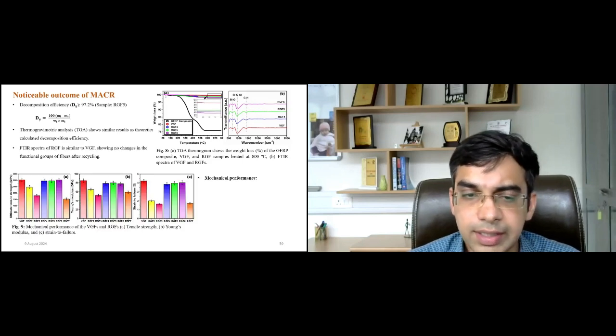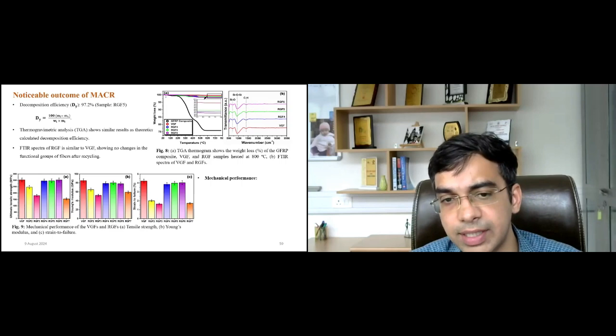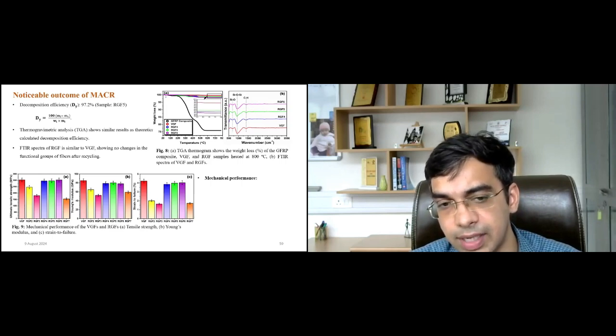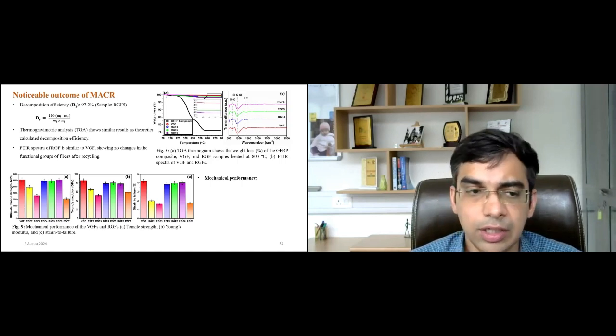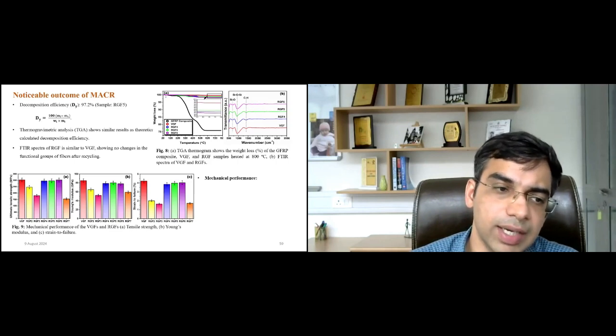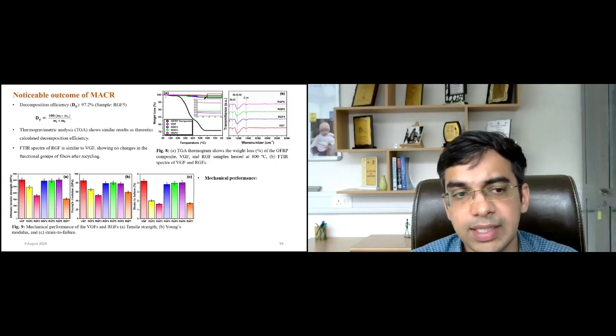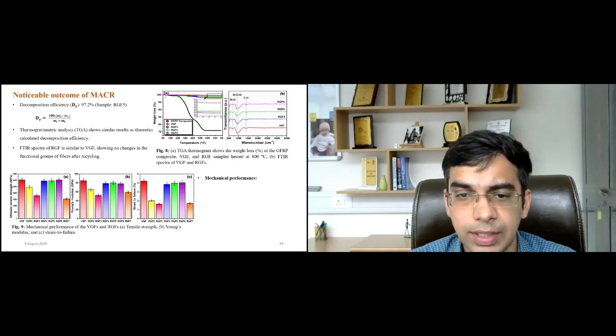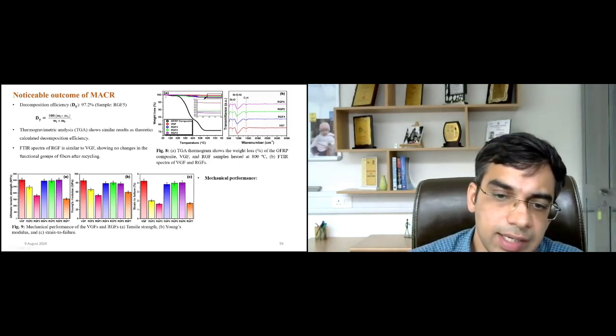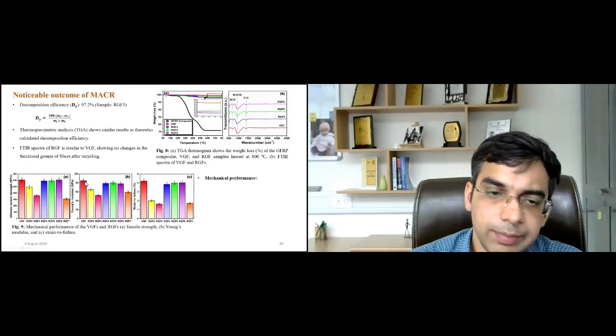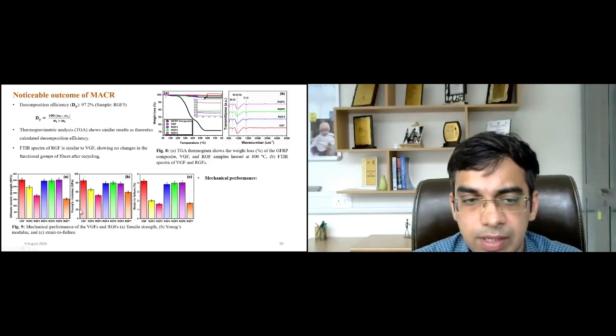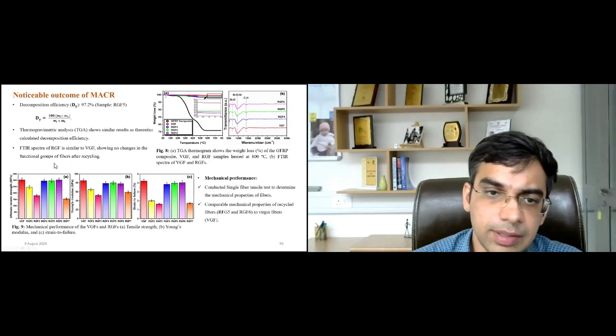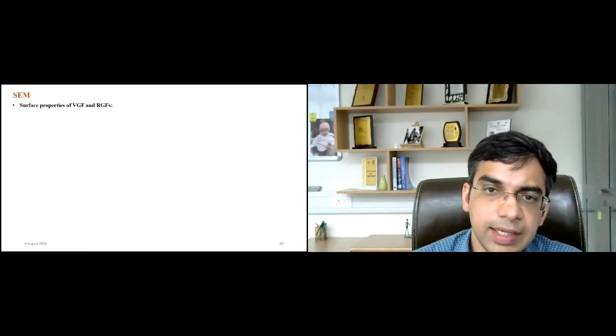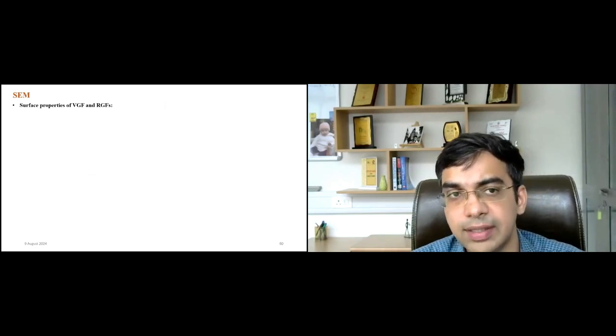We also conducted mechanical performance tests on single fibers. We extracted a single fiber and conducted the mechanical test to get insights into the ultimate tensile strength, Young's modulus, and strain to failure. At optimized conditions, say RGF 4, 5, 6, we could obtain almost at par properties with the virgin glass fiber. Here the comparison was done with the virgin glass fiber, and we conducted the recycling at several combinations which are already published in scientific literature.